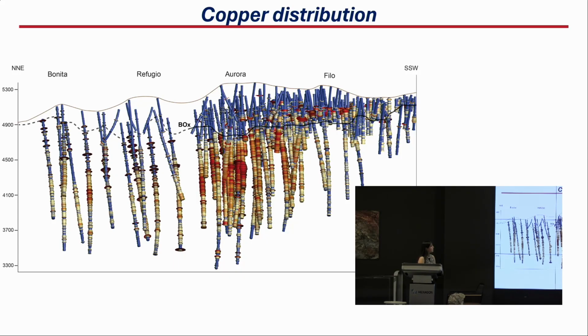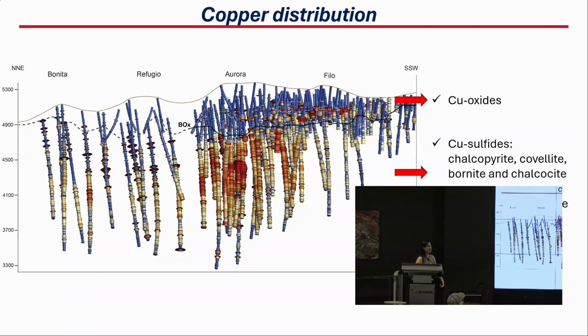So copper is hosted mainly in copper oxides in the top region, but we can also have a lot of different copper sulfides and copper sulfosalts, and we actually have copper in pyrite. Overall, regarding the content of copper, it's not extremely important, but we can actually get up to 4% of copper in pyrite. So it's a lot, considering that pyrite is widespread throughout the system.